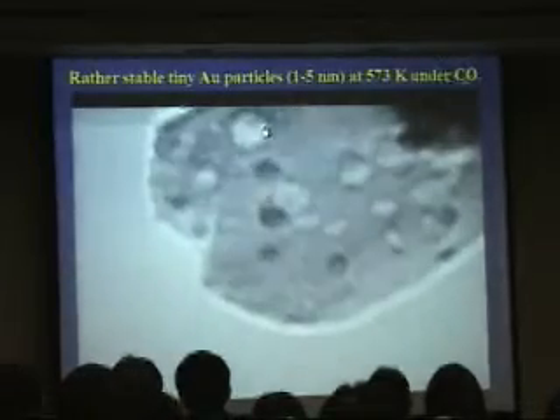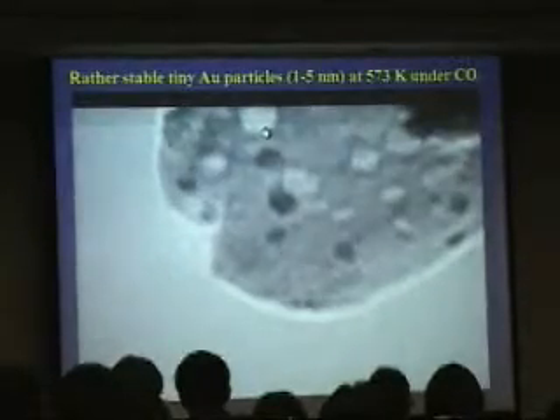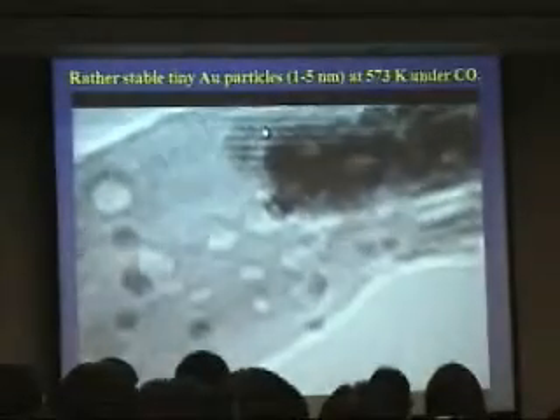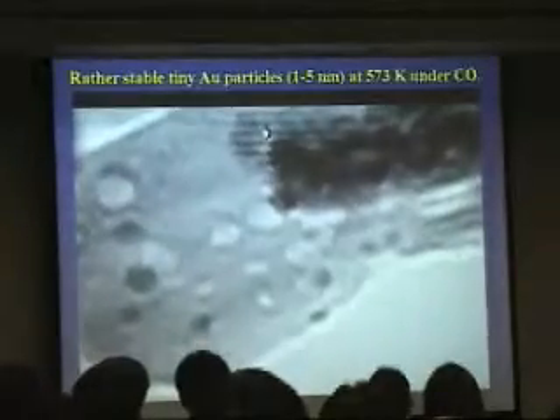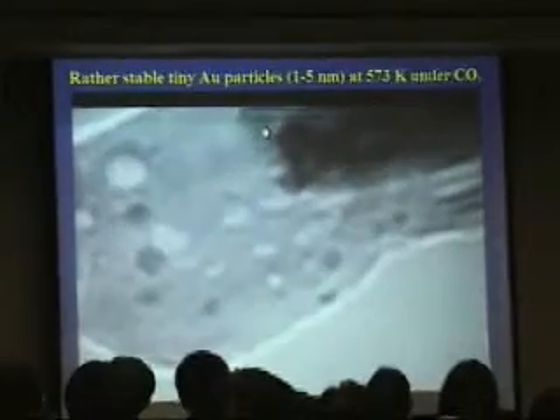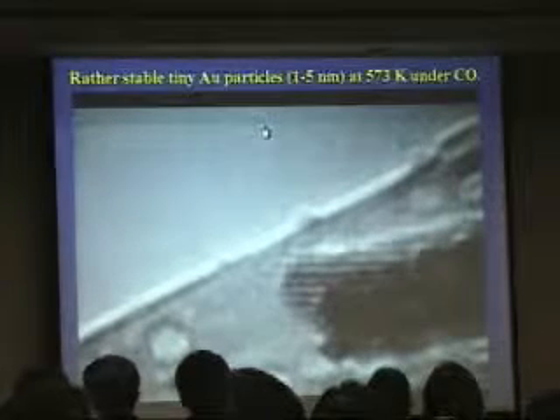So this is heating and also reduction with carbon monoxide, and you can find the vibration of the gold particles locally, and they try to leave the support to migrate or aggregate into larger particles. But the underlying forces from the rod-shaped ceria strongly hindered their mobility. So that's why at these high temperatures you can find no small particles meet together under this condition. So this is attributed to the strong bonding from the ceria support under these severe conditions.